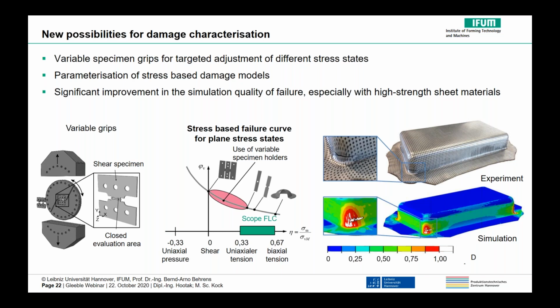With these variable grips, depending on the angle of tension, numerous different stress states can be generated in the shear specimen, the so-called butterfly specimen. This way, stress-based damage models can be parameterized in detail, as shown in the picture in the middle of the slide. This method can be used to characterize a much wider range of stress states than is possible with a classic forming limit curve, to improve the numerical analysis of formability, for example, in deep drawing.